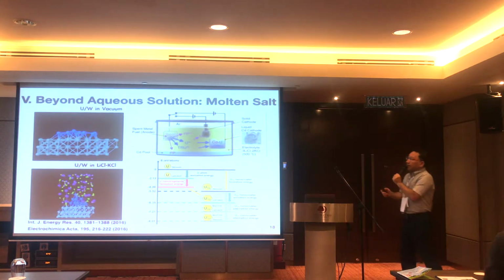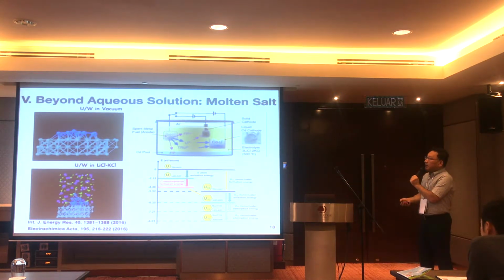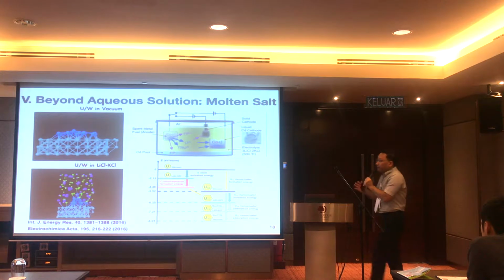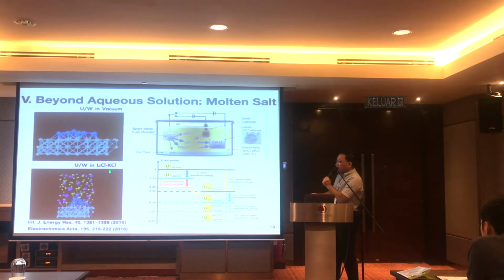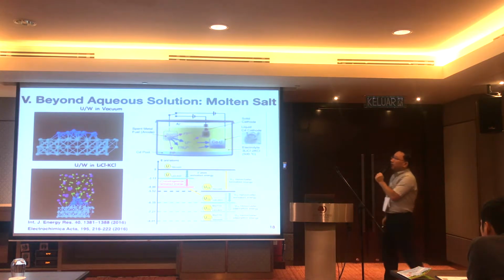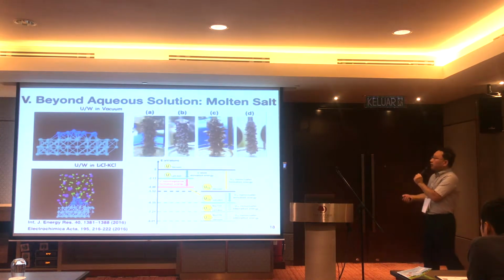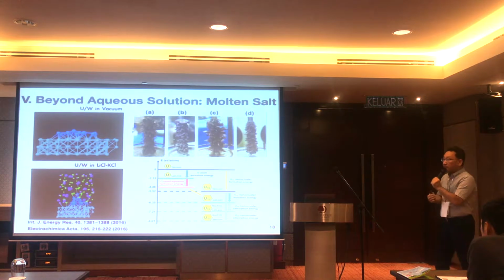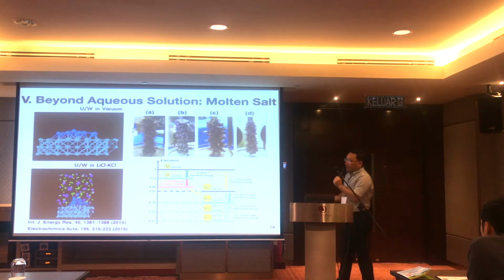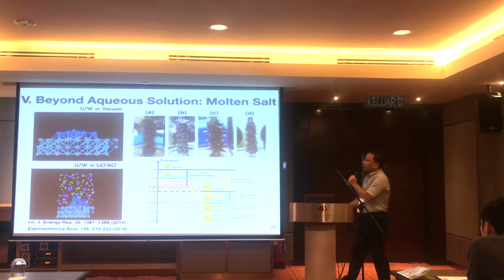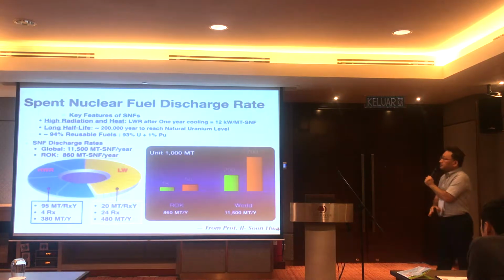So many people predict the topology, nucleation, or growth behavior using computations in vacuum conditions. That should be wrong. You have to incorporate the effect of chloride here, the molten salt effect. The topology is very different. What about experimental measurement? Experimentally, uranium grows in the dendrite topology, not the flat type. So this picture again shows that correctly simulating the medium is very important for predicting material growth.